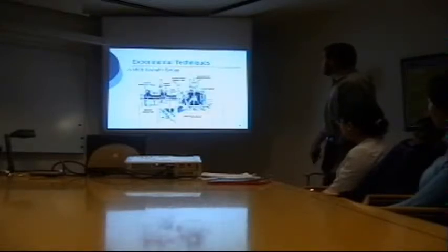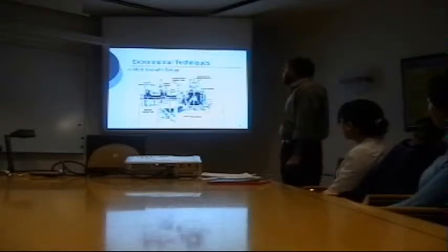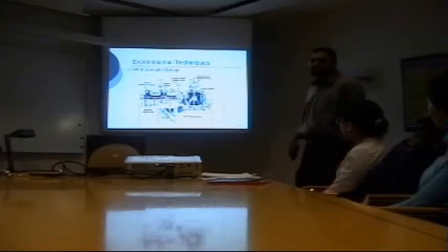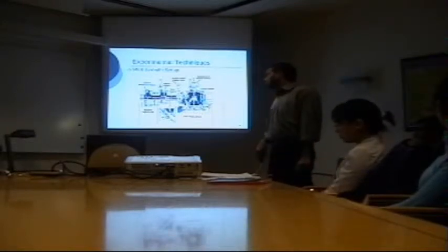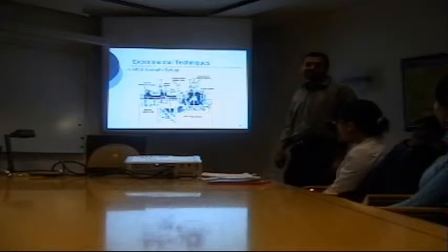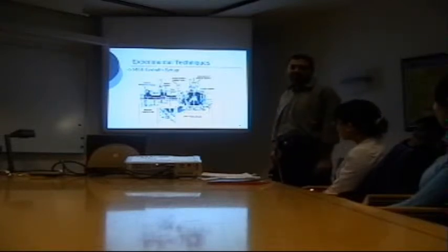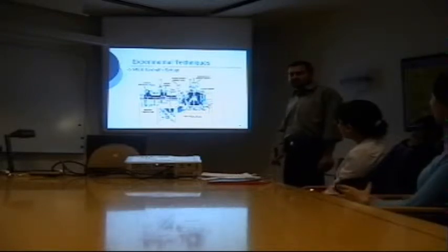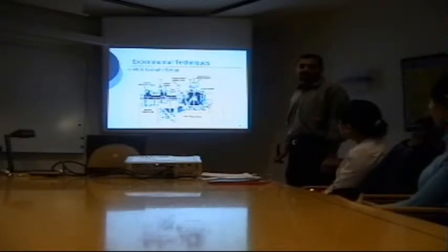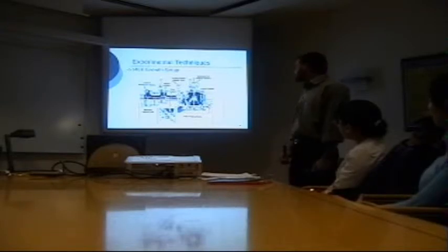Here in this slide, you can see the MBE growth setup. During this project work, we used a Balzers UMS 630 solid source MBE system equipped with a reflection high energy electron diffraction setup to monitor the growth conditions.